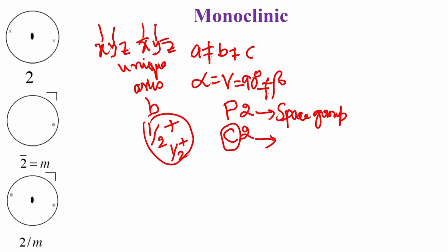Again, the definition of special positions might come up or they may not come up in a situation like this. For example, in a P2 system, if the object has a two-fold symmetry, then the object can sit on the two-fold symmetry, and as a consequence, in that situation the number of equivalent points will turn out to be equal to 1. That will be a definition of a special position. In a C centered lattice as well, there will be special positions. The special positions can occur both due to the point group operation and also due to the centering operation, and therefore, that needs to be examined more thoroughly, which we will do in the coming classes.